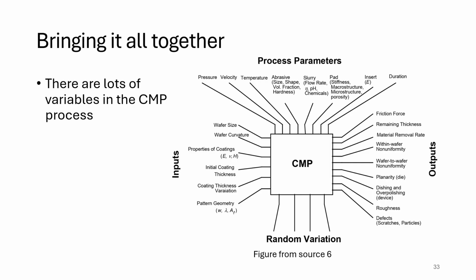To wrap it up, your main knobs are pad type and age, slurry composition and flow, carrier downforce, relative speeds of your platen versus your carrier, your pad conditioning rate, temperatures, and finally time. And all of these interact with each other. For example, a fresher pad cuts faster, but can raise scratches if slurry abrasives are aggressive. So it all needs tuning. Your material removal rate scales with pressure and velocity, and this is modulated by chemistry and pad microtexture.